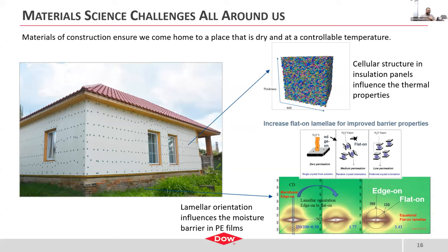One thing that we use at Dow to understand the cellular nature of the foams is X-ray microtomography. We do this both at Argonne National Lab and in-house with our tools, and we really use it as a way to quantitatively understand not just the size of the cells, but the orientation that they have relative to the manufacturing process, so that we can understand what variables we can play with around surfactant structure, chemical structure, processing parameters that can allow us to minimize the cell size in these rigid foam materials.